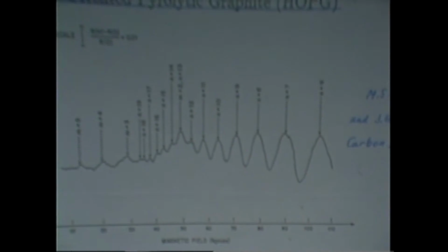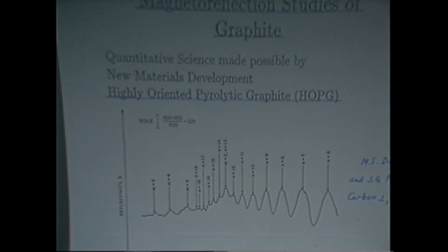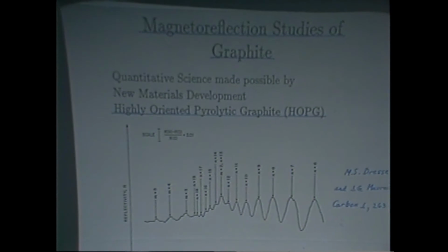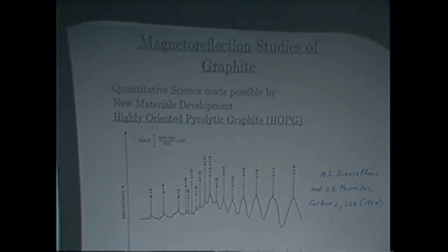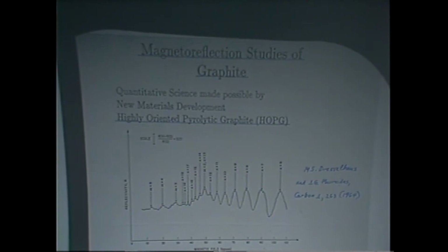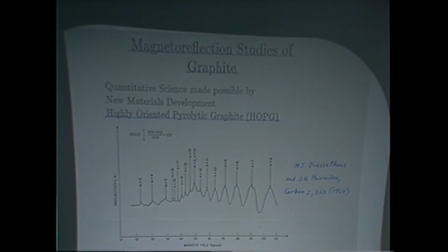But we were lucky. There was a fellow up at General Electric Laboratory who discovered how to make a new material. This is highly oriented pyrolytic graphite. Basically what he did was he decomposed a hydrocarbon on a surface, got rid of all the constituents by treating everything to high temperatures, so the only thing that was left was carbon, and then made it into semi-single crystal form, and actually got it quite crystalline by heating it to 3,600 centigrade. That's a very high temperature. And under pressure. It was not only heated to high temperature, but under pressure.